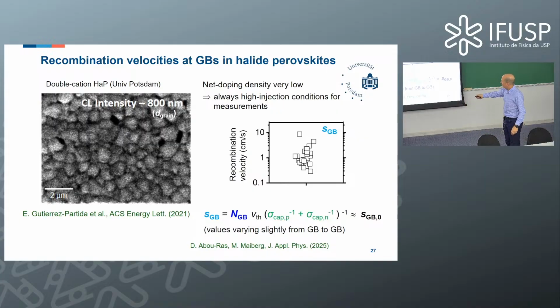So we have here the density of defects that make the Shockley-Read recombination, the corresponding capture cross-sections for holes and electrons, and the thermal velocity, which we assume to be equal for electrons and holes. Altogether, it gives again a kind of prefactor which slightly varies from grain boundary to grain boundary. These defect densities are very small because the doping density is very small. So we can also give some estimations for these values. But this is basically the reason why in this specific material we have a very special behavior.